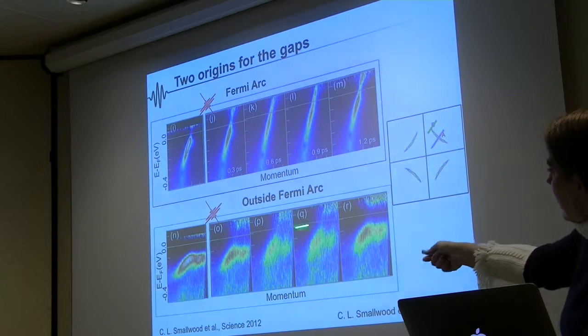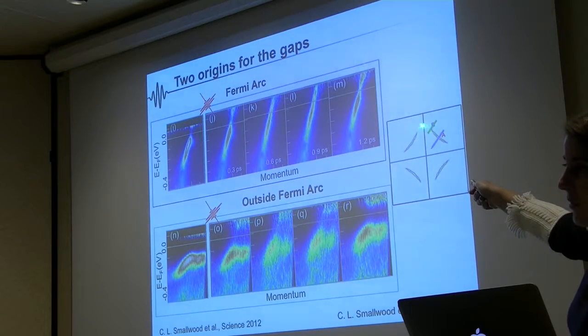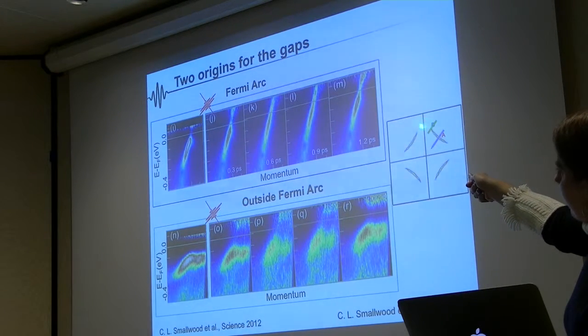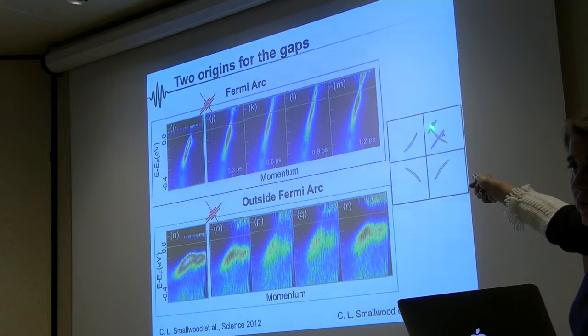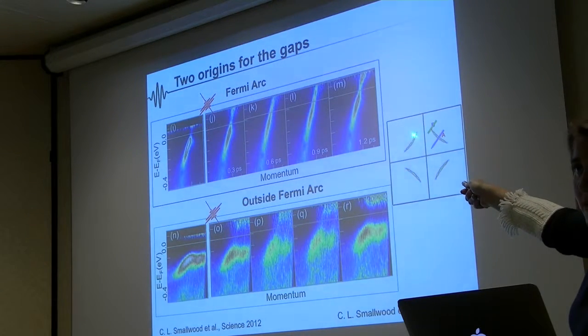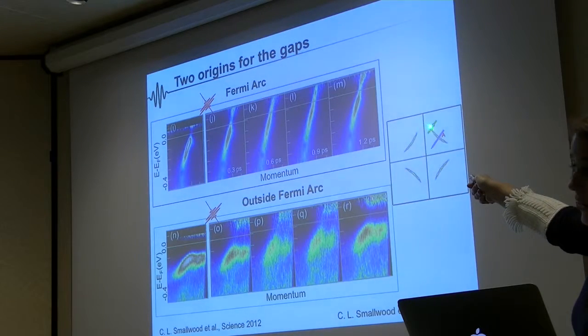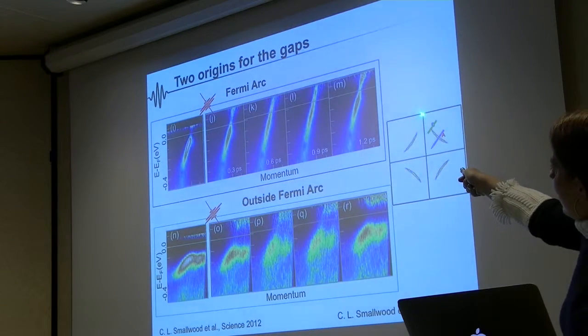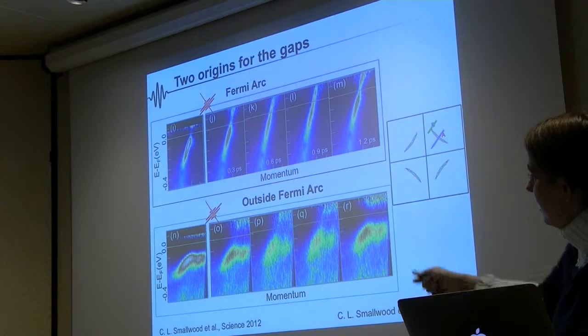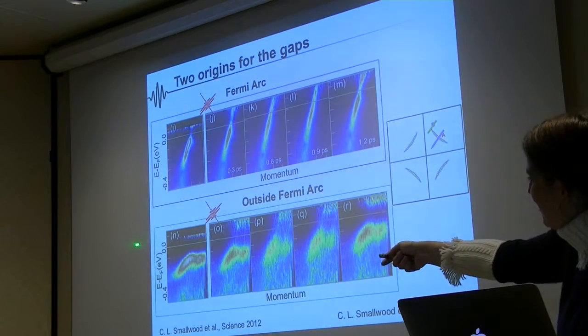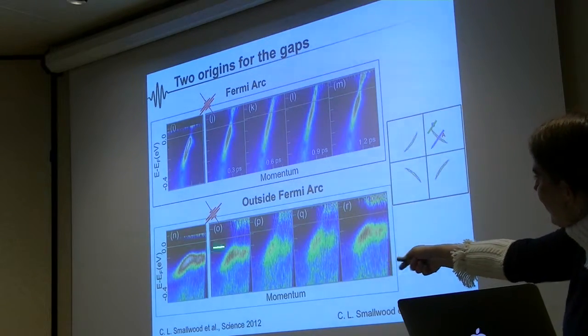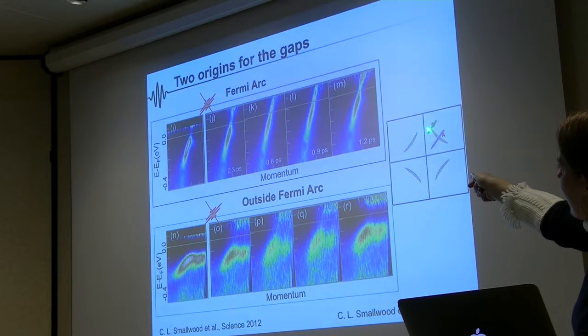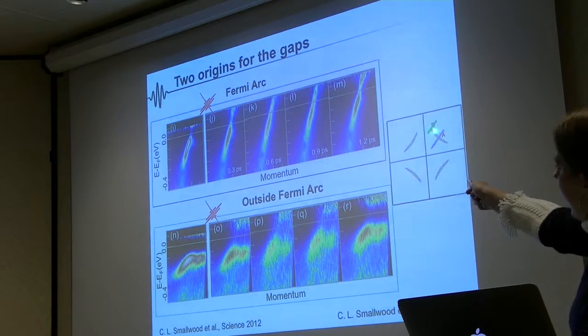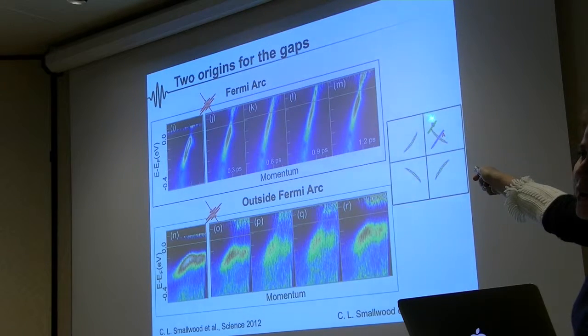But what you see here is that when you are sitting outside the Fermi arc, and this is true, we studied 3 angles outside the Fermi arc in the original experiment because we were limited by the probe of the laser. Now we have a new system that can do the experiment at 22 eV, so now we are actually studying this regime here. This is for next time, next conference. So here the interesting thing is that when you are sitting here, and this is true anywhere here, I can tell you now that it's true also here, although now we see some new state coming in when we do this part.